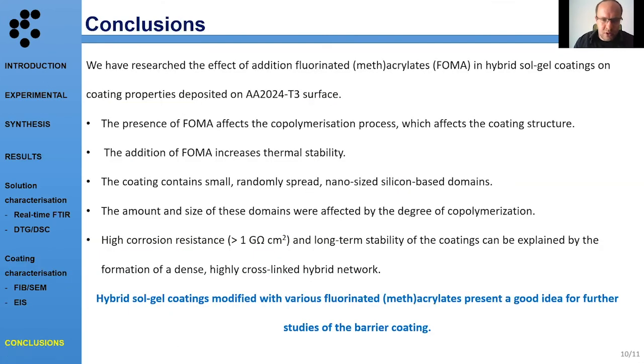So to sum up, we tried to modify this hybrid sol-gel coating with fluorinated methyl methacrylates, and we figured out that there is a very important parameter, and this is the copolymerization process, because this copolymerization process has an effect in different ways. First is, of course, the size of this randomly spread nano-sized silicon, but also the presence of these molecules changes the thermal stability of this coating.